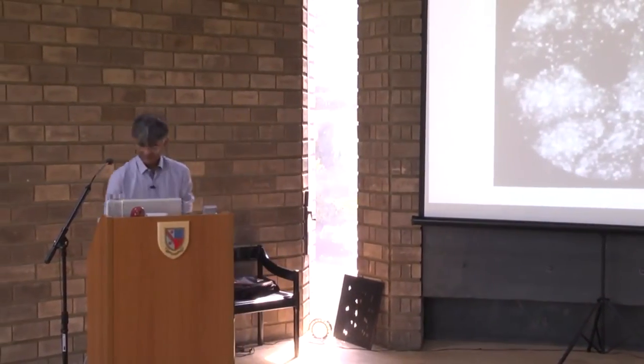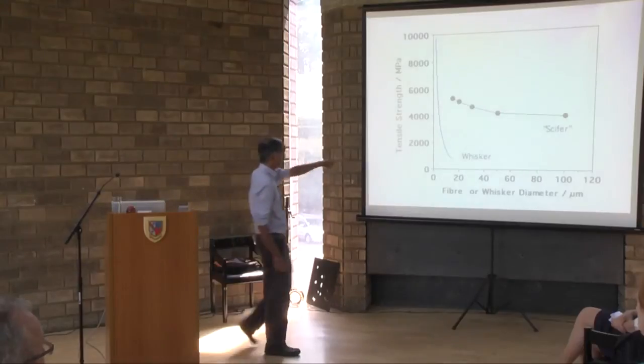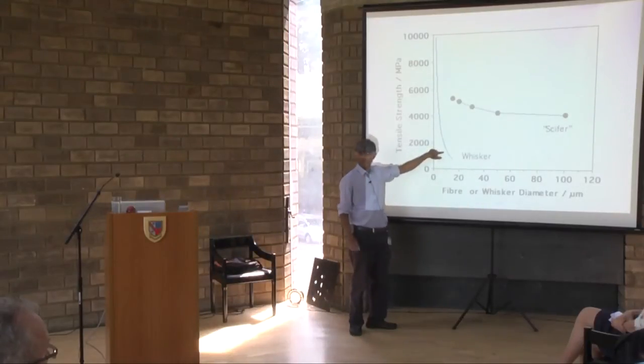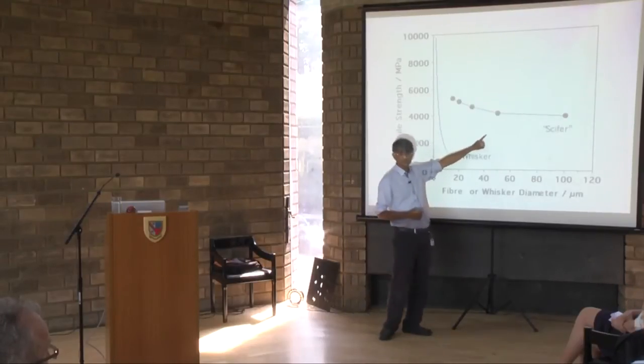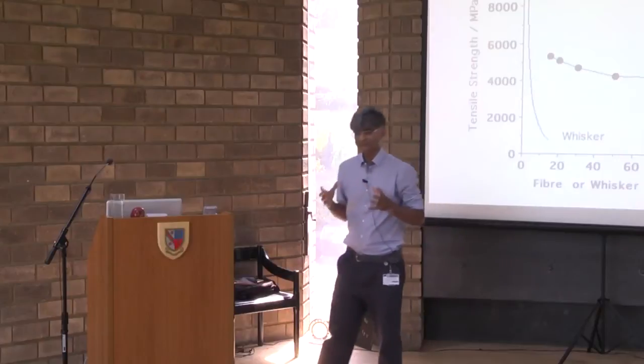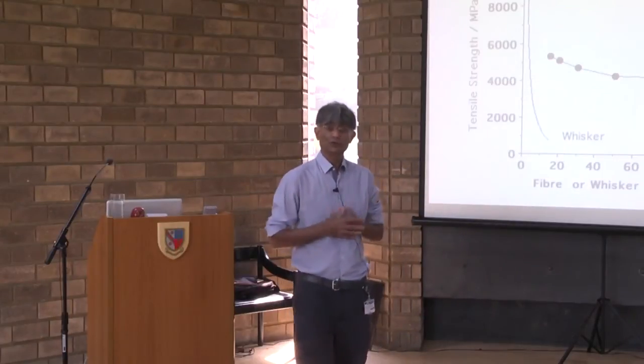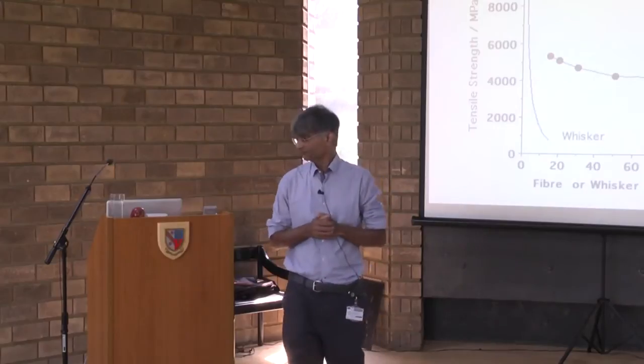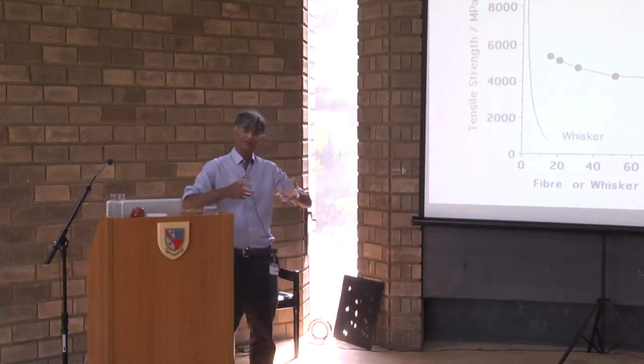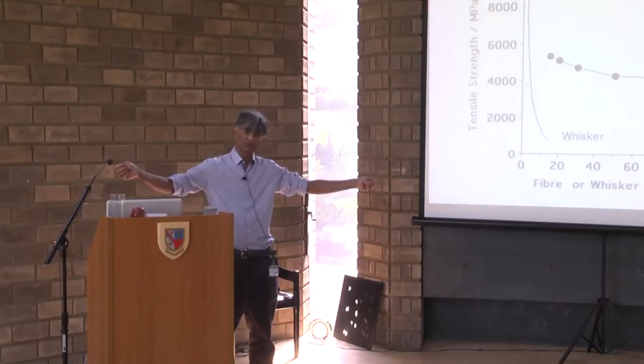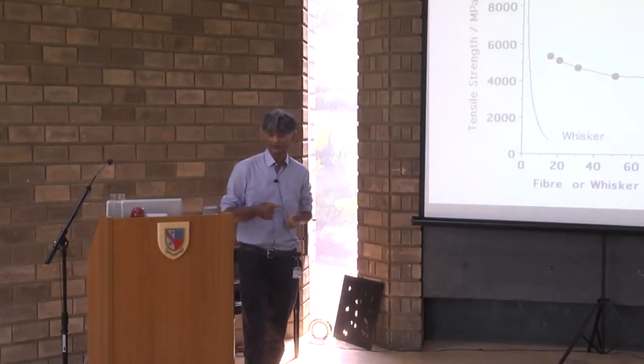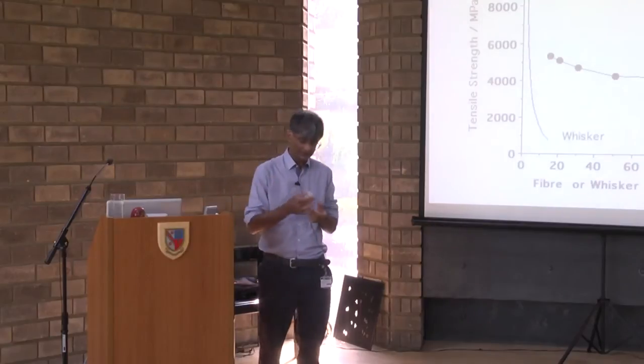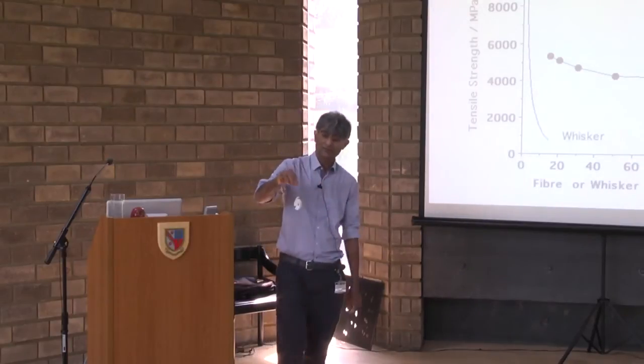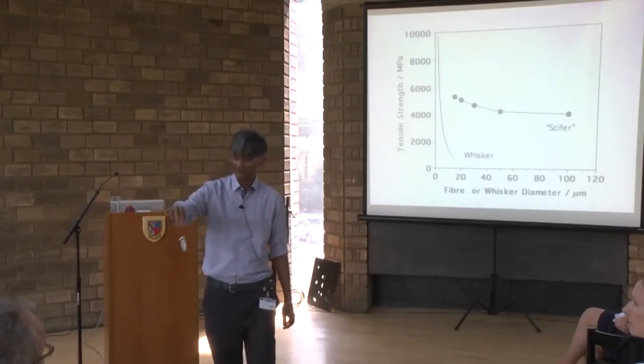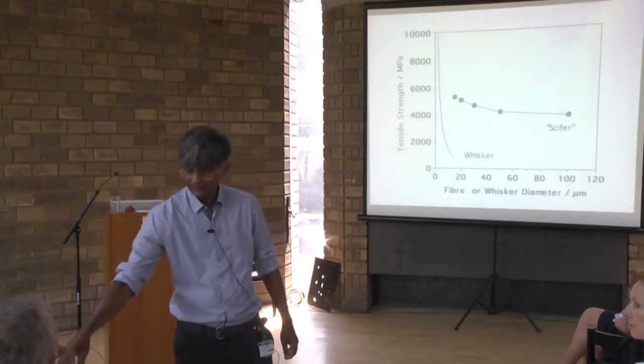When you do that, you lose the size sensitivity. So this is the first slide that I showed, where the strength collapses when you take a perfect crystal and you make it bigger. Here we are getting strengthening by introducing defects, and therefore there's no longer the size sensitivity. Now the problem with this is that if you stretch this out to 2 kilometers, you are going to end up with incredibly fine material, and here it is. I'll pass it around. This is 5.5 gigapascals strong, but you can see it's incredibly fine.